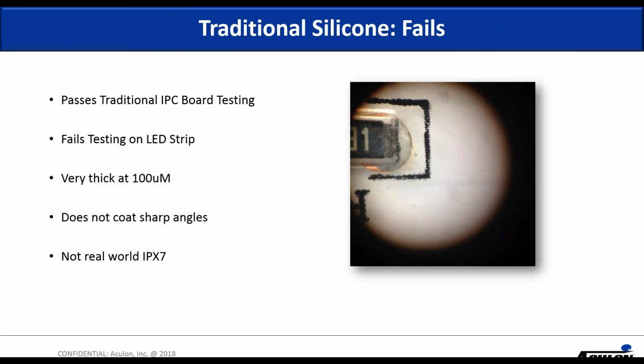We tested a common traditional silicone readily available from a major supplier. It passes the IPC board testing on a flat board with no problem, but failed the LED strip testing. And this was at a very thick, 100 micron thick level. And that's because these coatings, they slump. They have no feature or way to maintain their coverage on the corners, the high corners of the components. So even putting down multiple coatings, if you're not essentially flooding the board to the point where the component is just underneath the coating, it's not going to be protected. Those sharp angles are going to be exposed to water, and you're not going to get IPX7 levels of performance. Your boards are going to fail.